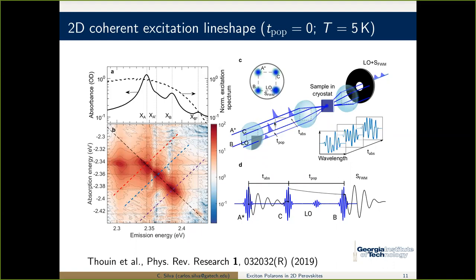And we're exciting a third-order nonlinear polarization in matter. Essentially, if you want a very brief classical explanation, a first pulse will excite the ensemble of oscillators in the system. Because it's a short pulse, all of the oscillators are going to start oscillating with the same phase as that pulse. But then, because of electron-phonon coupling, impurities, and exciton scattering, which is what I want to study here, you will start losing the overall mesoscopic phase of the system. You'll have dephasing. But before that happens, you come with a second pulse, crossed with the first pulse, and you still have a coherent response.